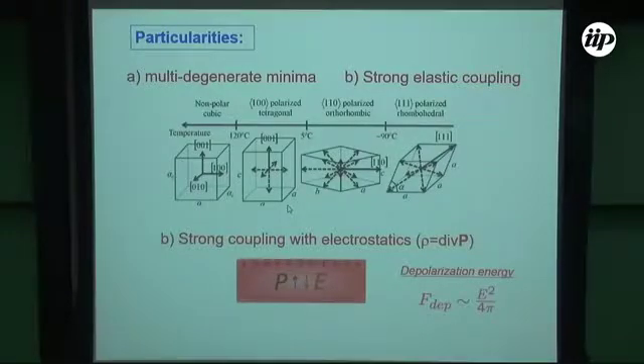Actually, polarization produces charges. This is easiest to see because the divergence of polarization gives charge, from electrostatics, and the most spectacular effect is the creation of the so-called depolarization field. Let's consider a finite size sample with surfaces; the polarization will terminate at the surfaces. At the point of termination, we shall have a charge, of course positive up and negative down, and this charge will create an electric field, like in a capacitor, directed opposite to the polarization, and it will actually prevent the creation of the polarization.